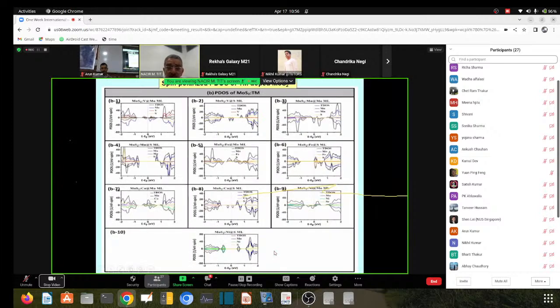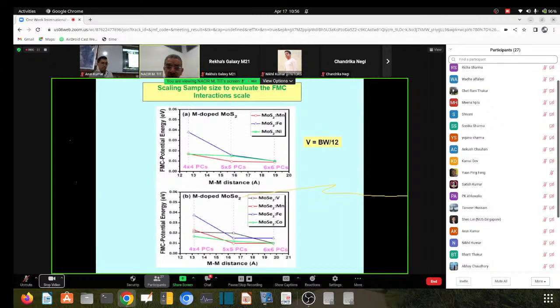So here we showed our results of density of states. Trust me, we investigated the cases of half metallicity, and here we show a summary of the potential of ferromagnetic interaction. The potential is obtained by taking the bandwidth divided by 12, because we have 6 neighbors, and as you know, for minus v till plus v, times the number of neighbors, minus 6v till plus 6v. Therefore, the bandwidth should be about 12 times the v. So V is the bandwidth divided by 12. That's what we call the potential of ferromagnetic interaction.